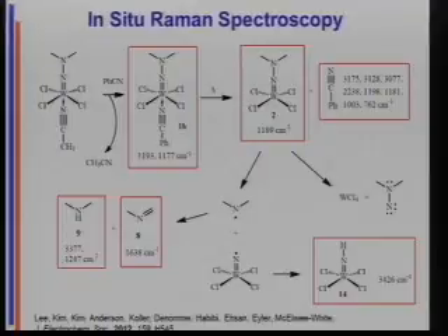So if you go back to what I said when I was talking about bond dissociation energies, I said the rate determining step is cleavage of that bond. But it tracks linearly with the bond dissociation energy, and bond dissociation energies are homolytic. For that plot to work, that has to be a radical cleavage, okay? And so if we're doing exactly the same thing here, it's another homolytic cleavage, I should make dimethylaminyl radical and that, a nitrogen-centered radical here. These two compounds, which we see in the Raman in the gas phase, are dimethylamine and the imine. These are the disproportionation products of dimethylaminyl radical.